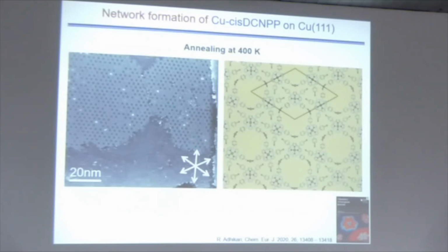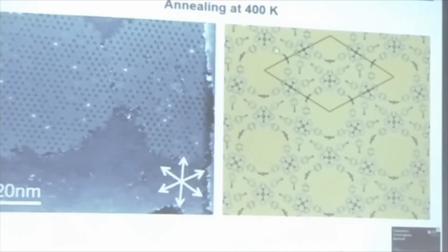And the interesting point here is that the reason for forming these networks is that you not only can insert the metal atom in the center of the molecule, but you also can coordinate the cyano groups of this molecule on the surface with copper adatoms.